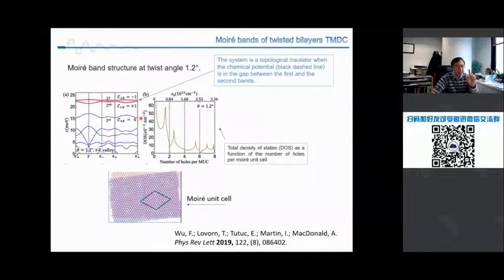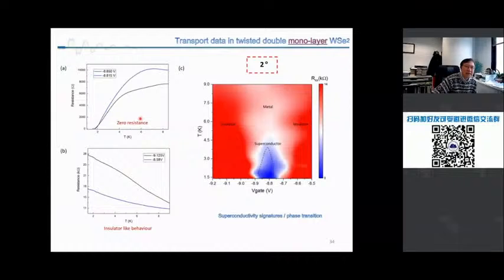And one thing is also important: TMDC has very strong electron-electron interaction. In fact, graphene normally does not have such effect. I'll show you some data. For monolayer by monolayer, it's all unpublished work. And you see nice phase transitions once you change the gate. Gate means the carrier concentration.